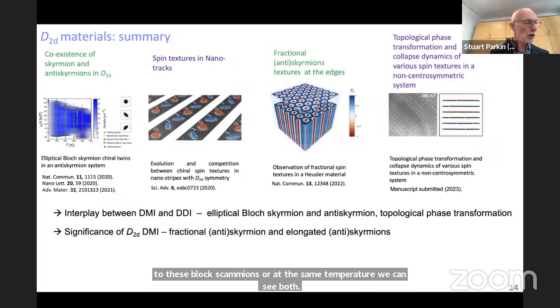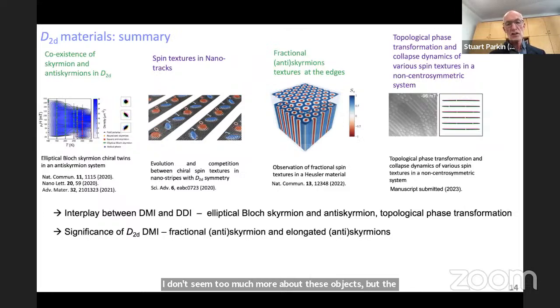I don't want to say too much more about these objects, but we found a rich physics in basically one compound, this manganese 2 platinum tin Heusler compound. We've seen the coexistence of skyrmions. Of course, we found antiskyrmions for the first time. We proposed we could use these spin textures on the racetrack that I'm going to discuss to store information. You could store zeros and ones in different topological spin textures, the elliptical skyrmion, antiskyrmion, elliptical skyrmion, and the antiskyrmion. We also observed for the first time fractional antiskyrmions, which were unexpected, at the edges of devices through a bulk boundary correspondence. And Jagannath has explored extensively the dynamics of how you can evolve from one type of spin texture to another, and looked at the topological phase transformations in that regard. So a very rich material.